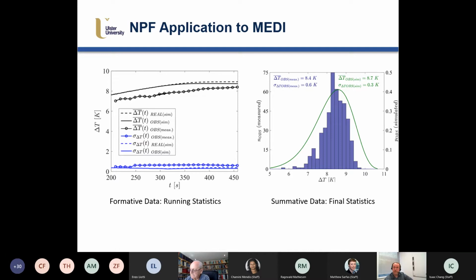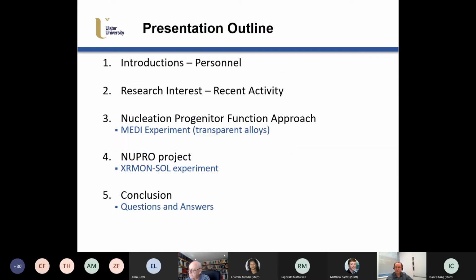Finally, through the principle of convolution, by taking all of these progeny functions as they complete their course, as they go through the entire range of solidification times, you're able to then combine them all and pool them to give you one curve here for the distribution of real nucleation events. And we compared that then to what was measured, and we had quite good agreement on that.